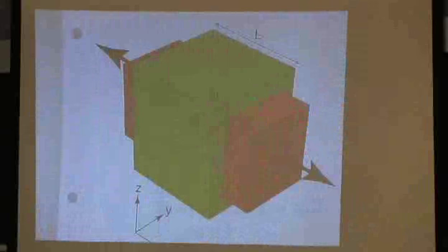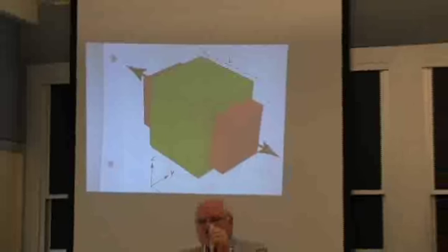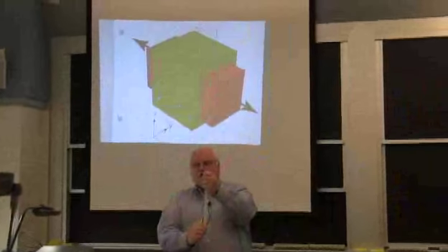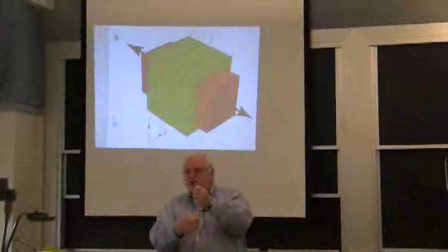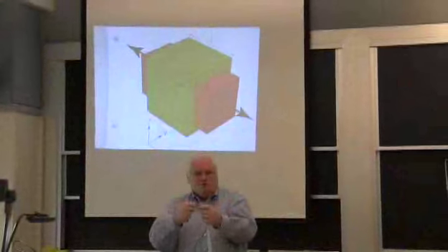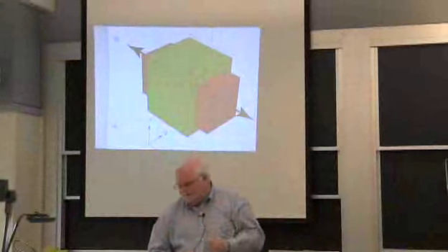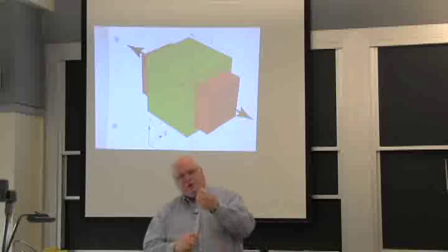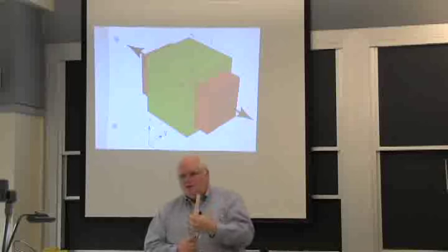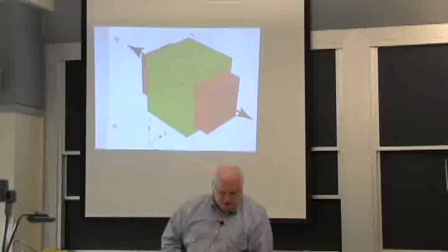So if I got a tensile specimen, here I have a piece of polyethylene. If I pull on it and it starts to stretch like that copper stretches, it will shrink in the other 2 directions, and you can see the copper shrunk. It necked down, okay? But even if I'm pulling on it elastically, there is a microscopic strain where it shrinks in the other 2 directions, and that's called Poisson's ratio.